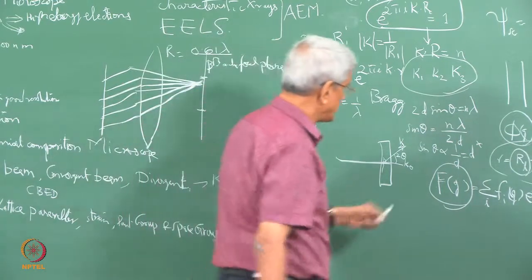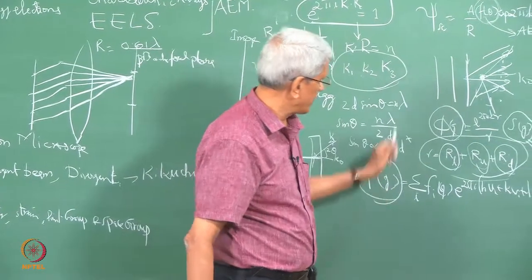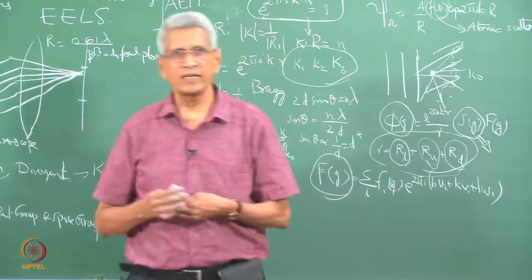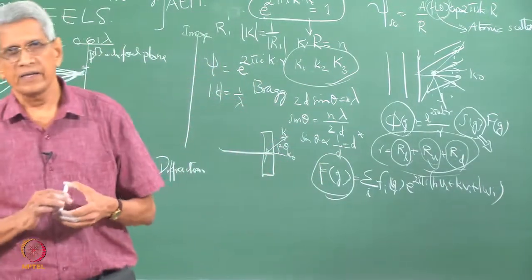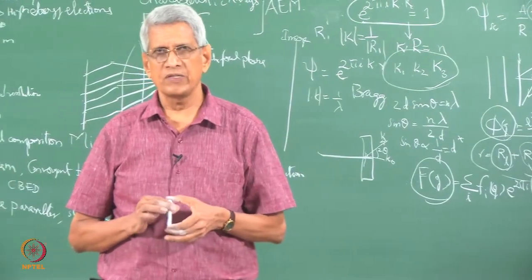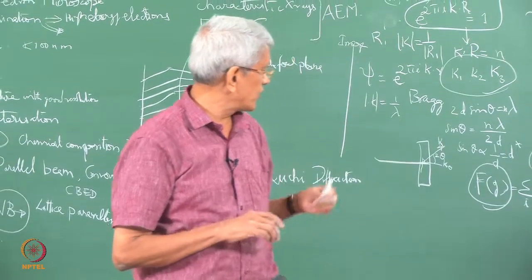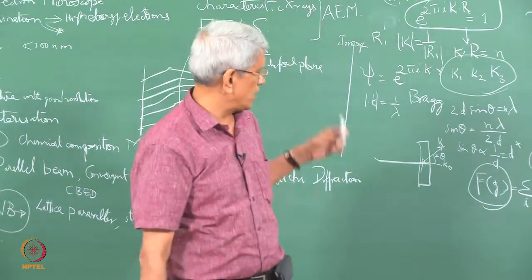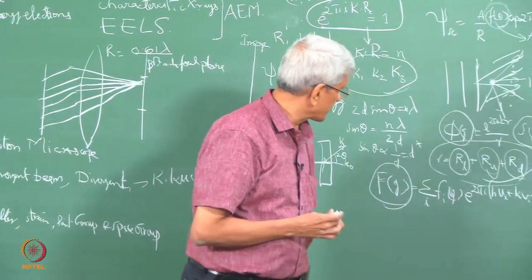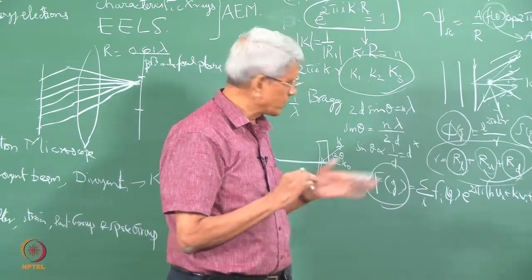Okay. What is essentially important is that in this Fg, we know that depending upon what positions the atoms occur, they give rise to special conditions, the extinction conditions, depending upon whether it is an FCC or a BCC crystal, for which particular reflections we will be able to see whether a constructive interference or a destructive interference will take place.